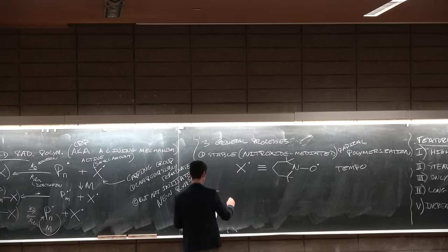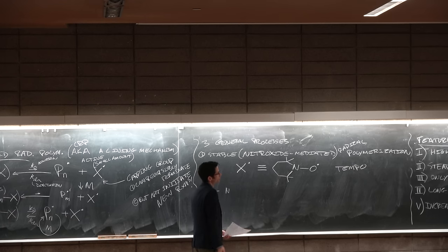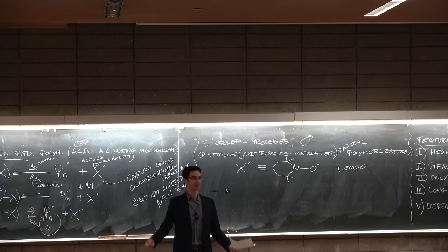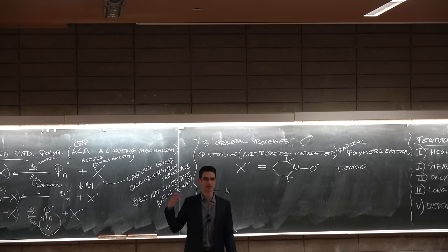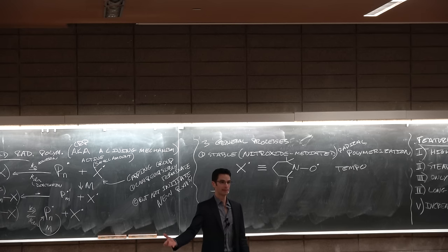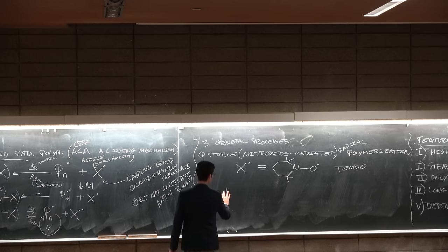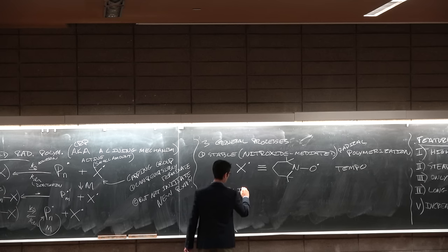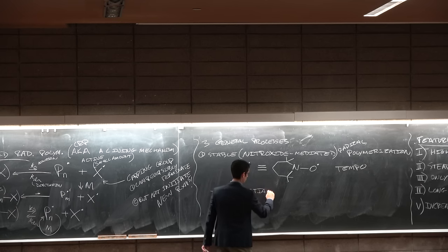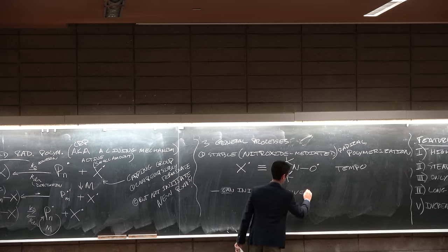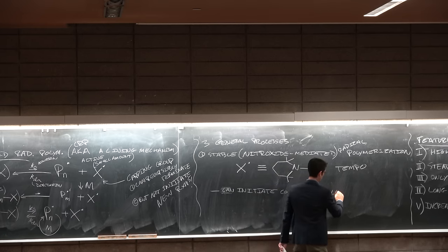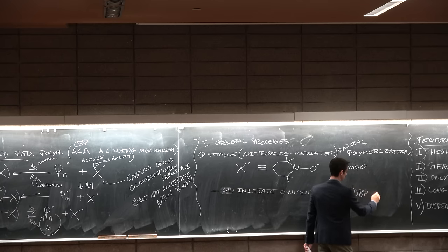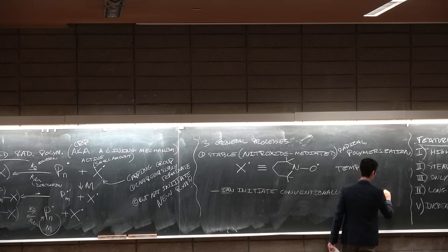So what are some of the features of this? How you could do this is you could have TEMPO in the reaction vessel at the beginning of the reaction, and you add your AIBN or your BPO initiator, and as soon as the reactions initiate, the TEMPO finds the growing chain ends and sticks onto them and terminates the reaction. But interestingly, you can initiate this conventionally, with BPO or AIBN,